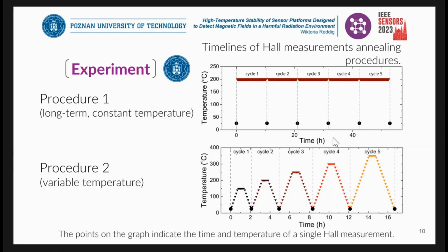And the other procedure, the variable temperature one, actually mimics the procedure that we applied to our irradiated sensors, to see how they change after irradiation with temperature. So it's just a direct replica of those conditions. Each point represents here a temperature and time of measurement of a single Hall measurement. And with the black dots, you can see the measurements at room temperature, which will tell us a lot about the permanent changes in between cycles.